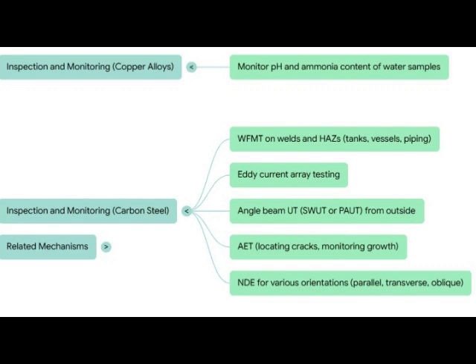And for the big carbon steel stuff, tanks, pipes, how do they check those welds, since that's the prime spot? The go-to method is usually wet fluorescent magnetic particle testing, WFMT. You apply it right on the welds and the HAZ. It's great for finding surface or near-surface cracks. Okay. Alternatively, or sometimes in addition, they use specialized ultrasonic testing, UT, angle beam UT, like shear wave or phased array. They send sound waves in from the outside to map out any flaws inside the weld. And for really large vessels, there's also acoustic emission testing, AET. Acoustic emission. Listening for cracks. Pretty much. AET uses sensors to listen for the tiny, high-frequency sounds that a crack makes as it grows under stress. It's fantastic for monitoring if existing cracks are active and finding the hot spots.